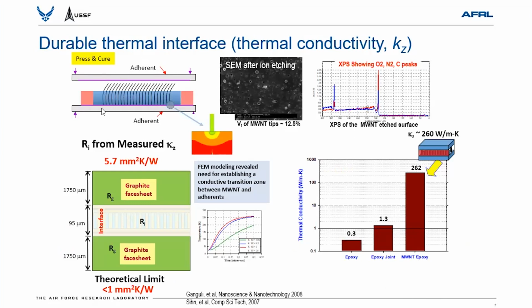This is the bonded joint, and this idea I got motivated by Dr. Ed Silverman from Northrop Grumman. He told me that if the bonded joint through thickness thermal conductivity can be improved, say traditionally 1 watt per meter Kelvin to 10 watts, there's a big savings, say $1 million per satellite. So that's the big savings over the lifetime of a satellite.